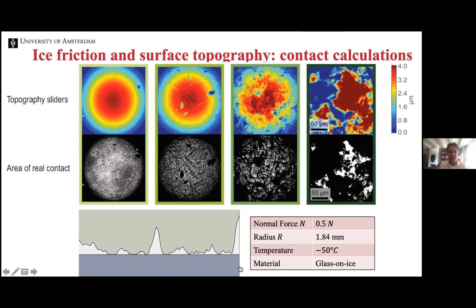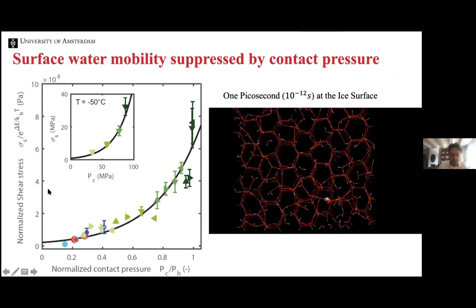And it turns out that the contact pressure is very important in what happens, because if you look at the normalized shear stress, so this is basically the friction force normalized by its Arrhenius behavior, as a function of the contact pressure, you see that the shear stress goes up relatively steeply if you increase the contact pressure. So if you touch the ice only with a couple of points of the roughness, it becomes very difficult to skate, and that's not because of the plowing, but because you push out this layer of very mobile molecules if your pressure is too high.